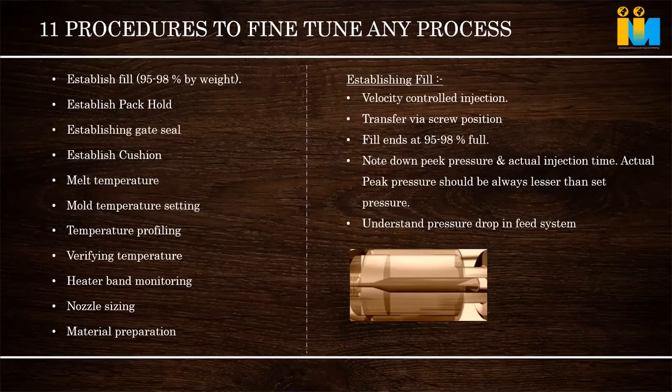Generally in a molding shop people say nylon 260 degrees, PP 220 degrees. What I mean to say is we have to select the melt temperature based on the actual raw material data sheet, not generic values. The base polymer may be the same, PC in multiple grades, but whatever additives and fillers there are will change that, and that also changes the melt temperature. So proper selection of melt temperature is very, very important.